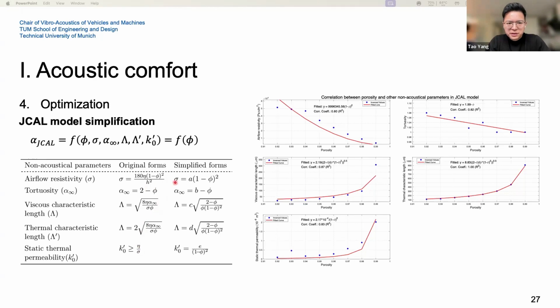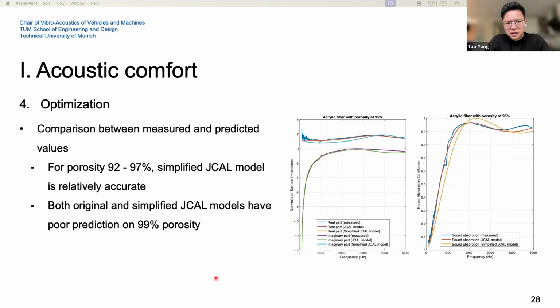If the material is the same, we can consider the rest of the part besides porosity as constant. So I set them as constants for different acoustic parameters, from A, B, C to E. Then I made measurements for different porosity materials, got their acoustic parameters, and used a simple regression method to plot the relationship between porosity and such acoustic parameters. Then I validated the simplified JCAL model. It looks quite okay, and for porosity from 92 to 97, the simplified model is quite accurate.